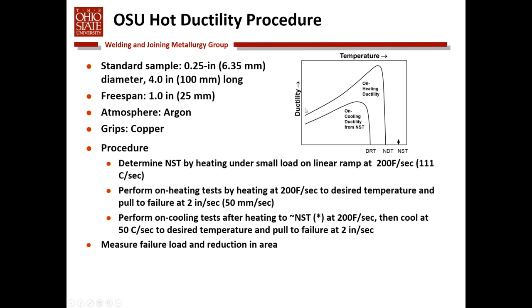We then perform on-heating tests to develop this particular curve and identify what the nil ductility temperature is. So this is the point at which the ductility of the material, based on its cross-sectional area of failure, is essentially zero. Once we determine that value, then we perform on-cooling tests after we heat to the nil strength temperature or very close to it, and then cool the sample and test on cooling to develop what's called the ductility recovery temperature. So when this ductility starts to increase again, it means the liquid films that were formed at elevated temperature start to re-solidify and the material retains its ductility.